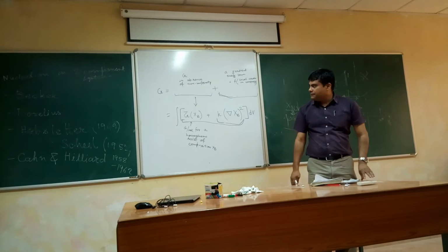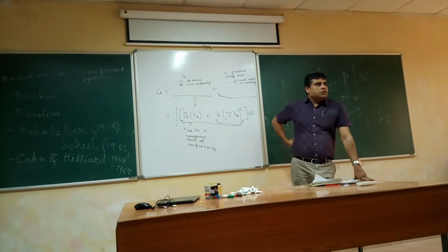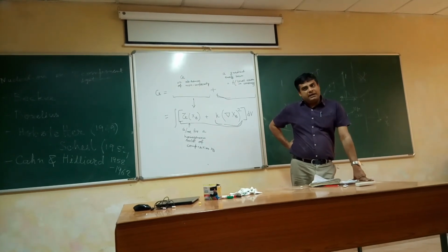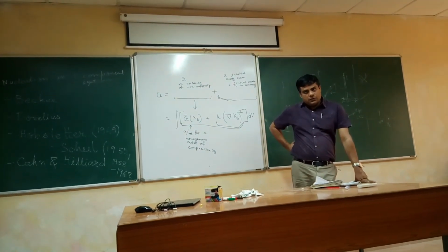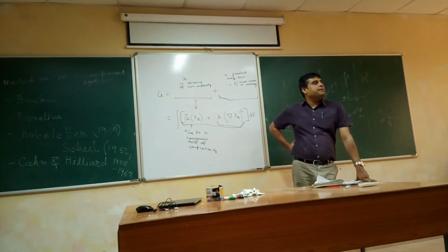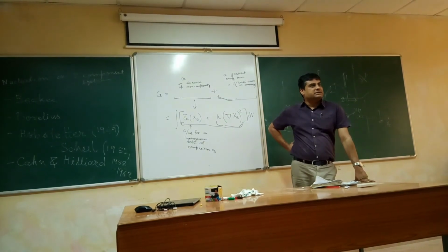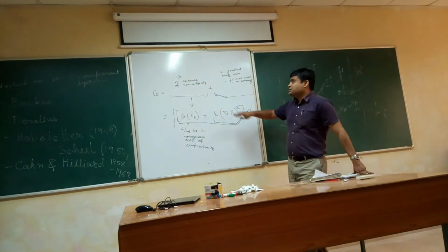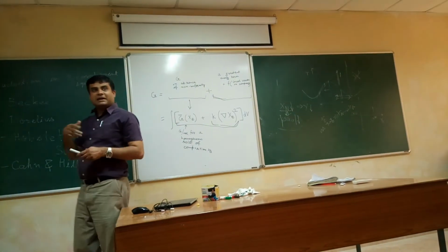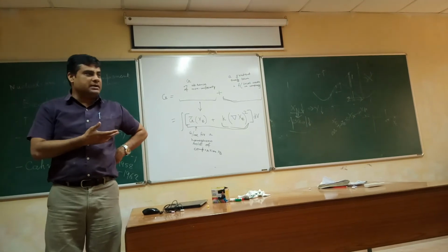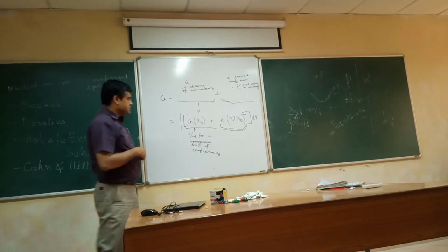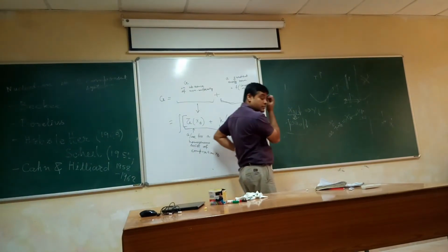And this Gibbs free energy, or this approach of Cahn-Hilliard, is applicable for solid state also. Only thing is the product, the precipitate or nuclei that we are considering, because we are using one single function of Gibbs free energy, that means we are assuming the precipitate also has the same crystal structure as that of the matrix. So here also that assumption stays if we write only one equation.